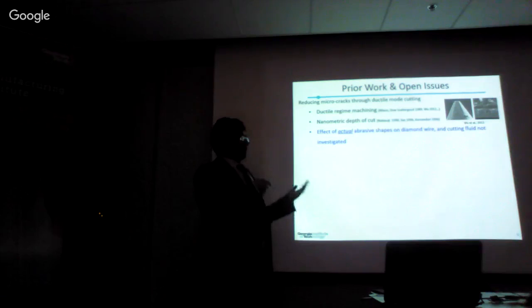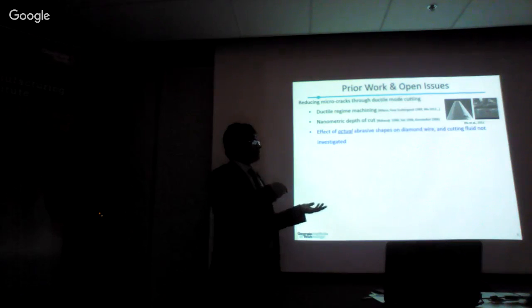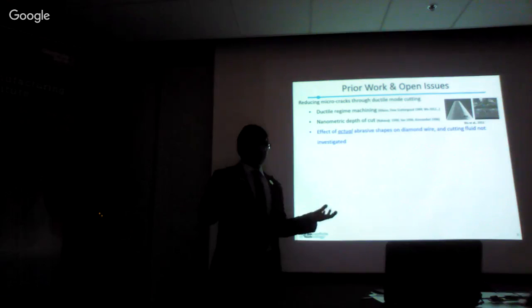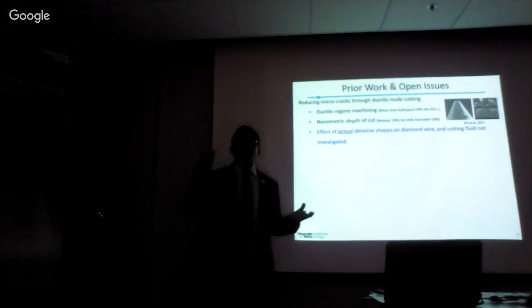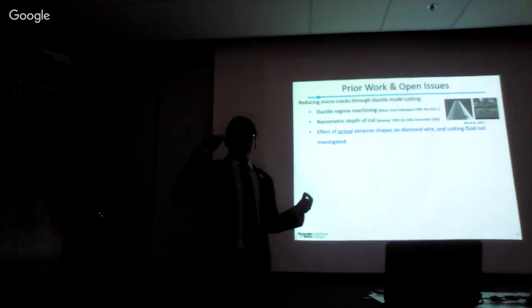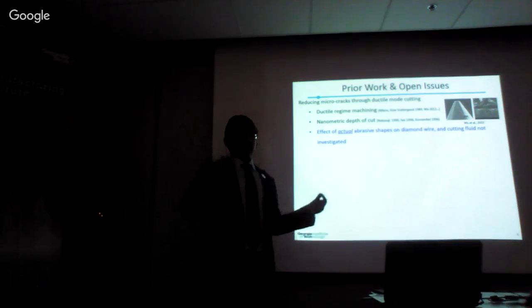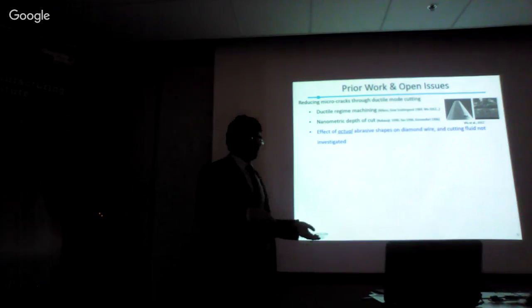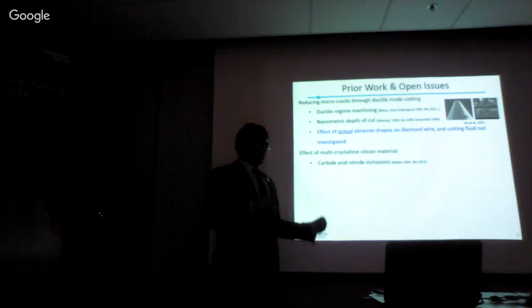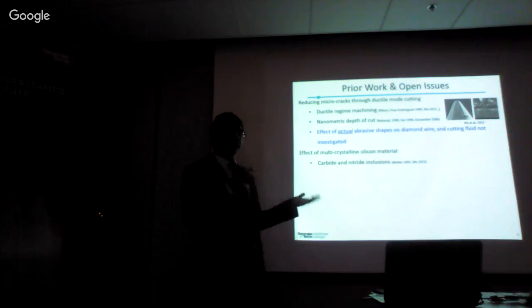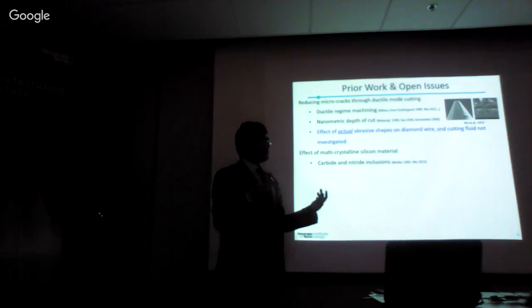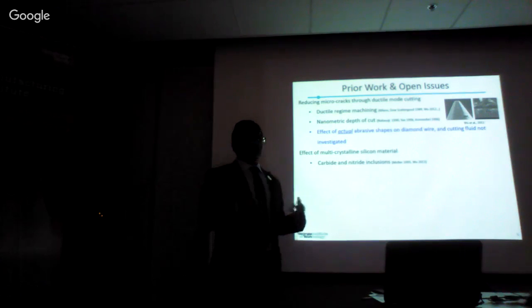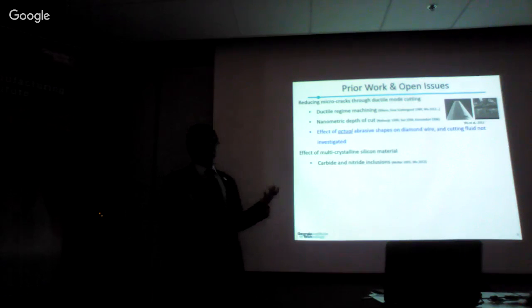There is some prior work done in our group on the effect of abrasive shape using idealized shaped indenters, as shown here, which could be conical or rounded, but no work had been done on the effect of actual abrasive grit shapes on the industrial grade diamond wire, which is what I'm doing in my PhD thesis. Moving on to the next challenge, which is the effect of multi-crystalline silicon material. As I was speaking earlier, multi-crystalline silicon has a lot of grain and twin boundaries, as well as carbides and nitrides as inclusions.